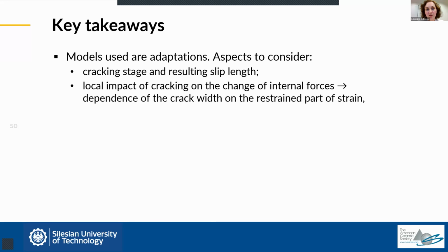Then, of course, we need to remember that in such elements, we don't have full restraint, we have only partial restraint. It means that cracking will have only local impact of internal forces. So as a result, the crack width will not only depend on the applied reinforcement, but on the magnitude of load. So we must be able to accurately calculate the value of this load. And also we must remember that this type of load, in contrary to service load, is a sustained load, which has an important effect on creep. That's why we should take into our calculations the effect of creep and how it influences the stresses.